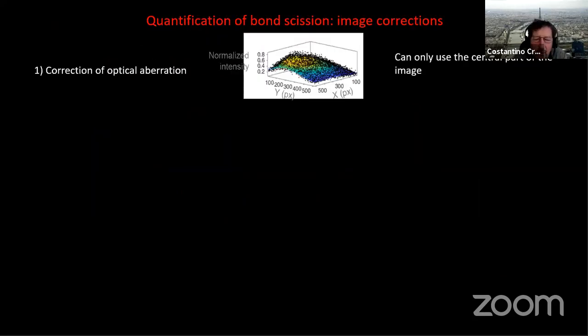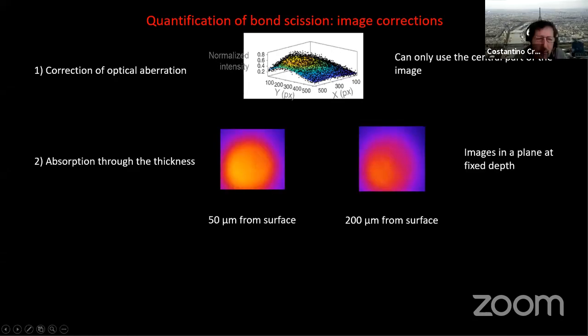Now, let me go back to quantification. Again, we can look at images. I've shown you images, but can we really know how many we break? We need to be a little bit careful with that. First of all, we are measuring, of course, the scanning image. Now, there is optical aberration, so you have to really use a calibration sample. We typically use a grid, which is used by microscopists, where every single point has the same intensity. We correct our images by that grid to make sure we don't have regions in the image where we have artifacts. The second thing that we need to correct is the absorption.